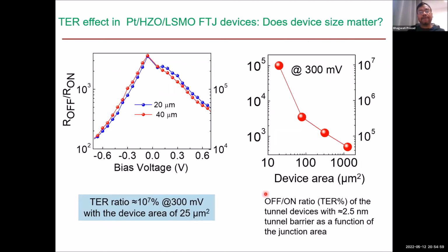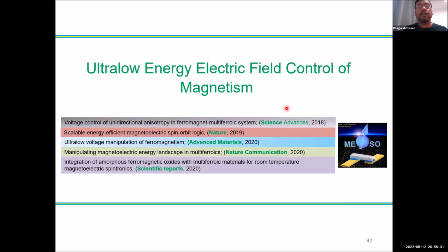Okay, so also what we found is that the device size matters. When you reduce the device size, the on to off ratio increases, because with a smaller device you can switch them uniformly at a given voltage, and you can also reduce the leakage current, and that way you can improve the TER. So this is also better because we want to make very small devices. Recently at Western Digital, we have tried to make a 100 nanometer device, and we could show that we can switch them. Okay, so this was about the ferroelectric tunnel junction.